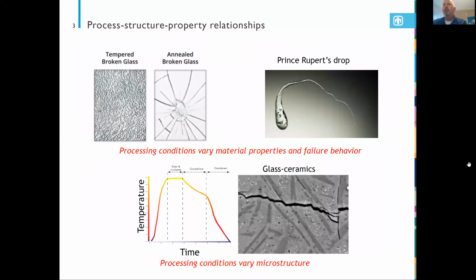So in terms of those process-structure-property relationships, I wanted to highlight just a couple of them. For instance, one of them is tempering glass. We're all very familiar with tempered glass. It is consistent with your windshield to some degree, given your windshield is a laminate, but the tempering process is intended to give a very particular result during fracture. You intend on having very small pieces produced from what remains of a fractured glass. That's a lot safer than having large shards that would be consistent with an annealed glass.